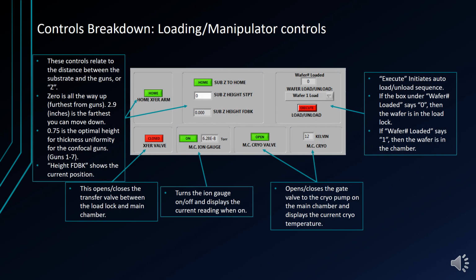This section allows us to initiate automatic sample load and unload, control some gauges and valves, and set our substrate height for our process. When the load lock is below 2e-6 torr, we can load the chuck very simply by hitting the execute button where it says load and unload. This takes about 1 to 2 minutes. Once you initiate it, you will see most of these controls gray out so that you can't interact with them. Don't try to do anything else while loading occurs or you may cause it to freeze. Once the sample is loaded, you'll be able to push the execute button again to unload.